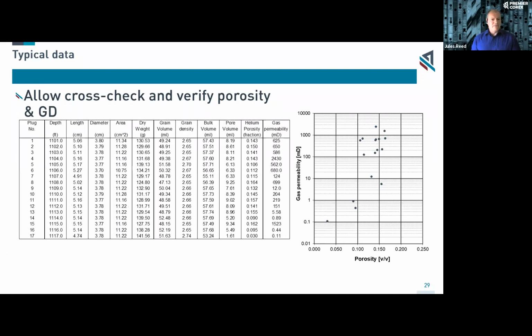We might have length and diameter data and dry weight. The dry weight allows us to check the grain density and make sure that those agree, and we can then look down the grain density data and we see one sample that is significantly different than all the others down at the bottom there at 2.74. And we can begin to ask questions about that one sample, but we also see that it's the one with the lowest porosity, so it might be expected as well. So the data still potentially stands. Let's look at other